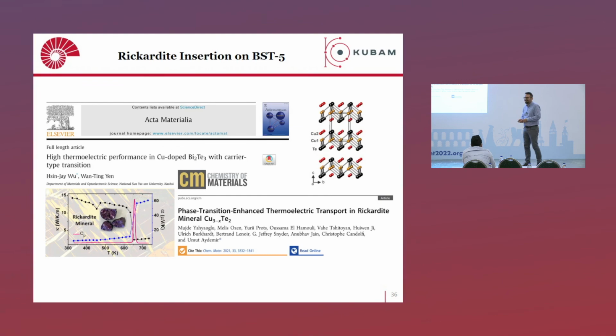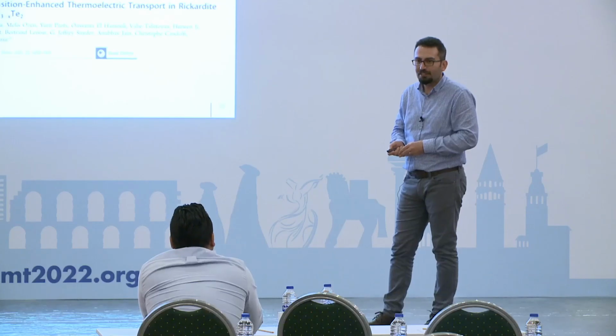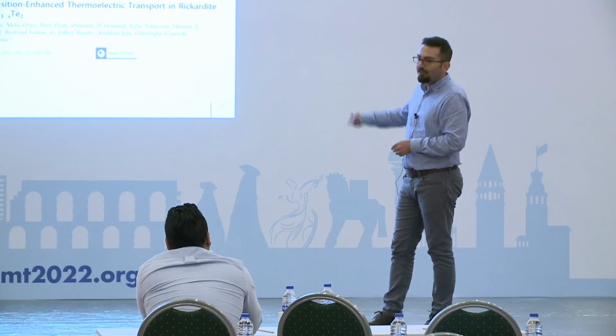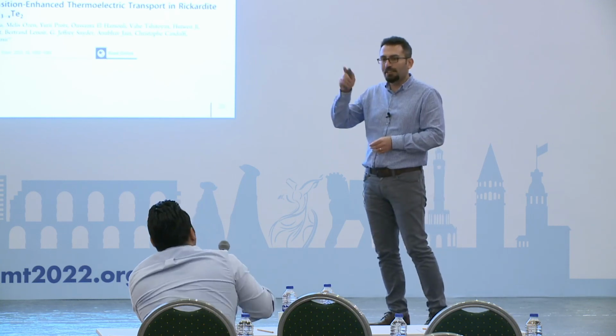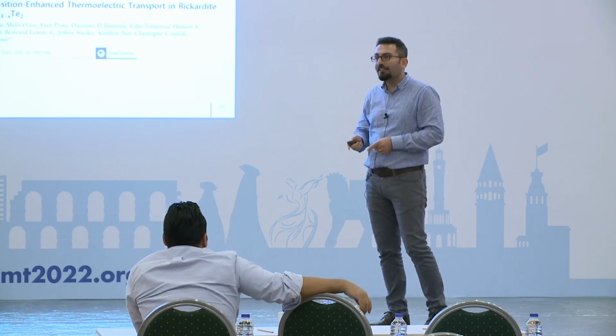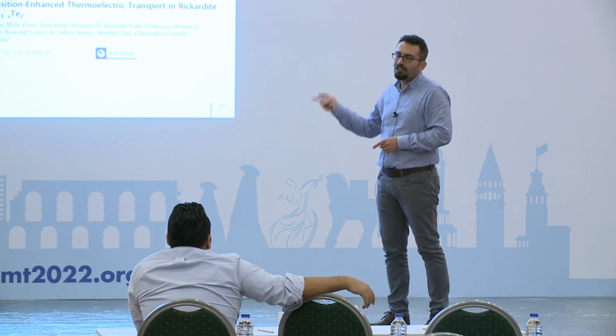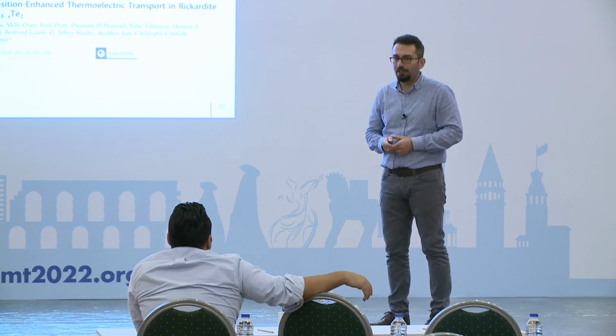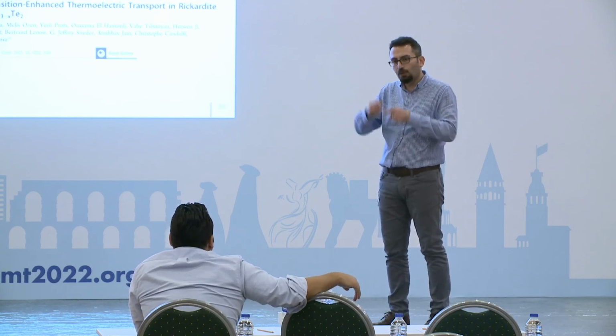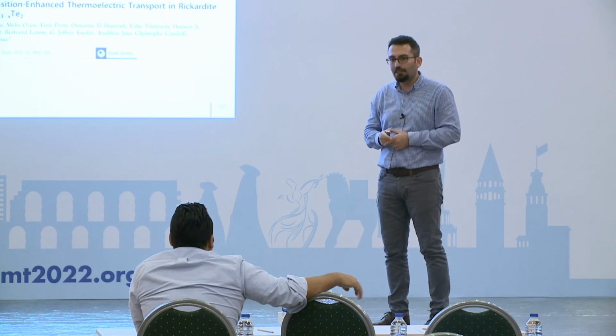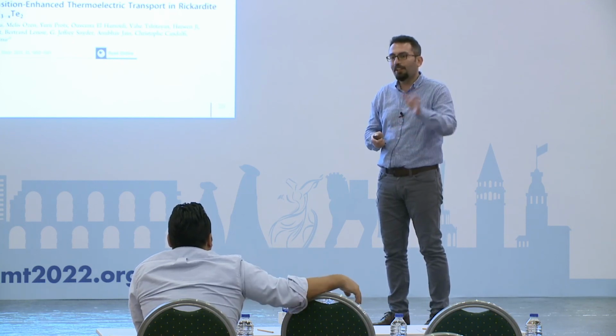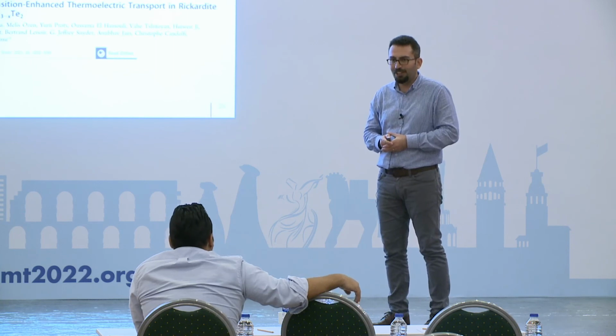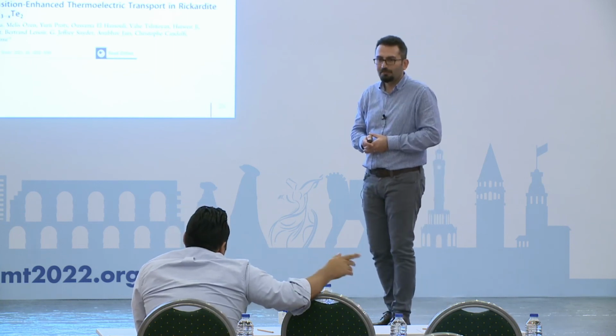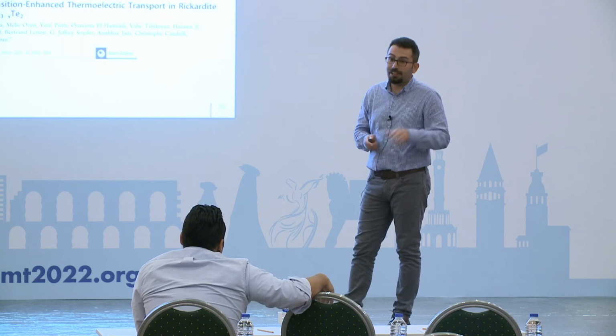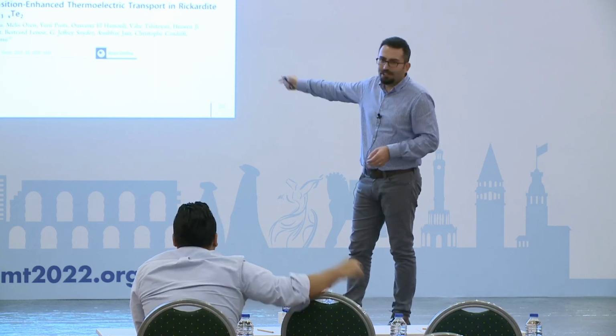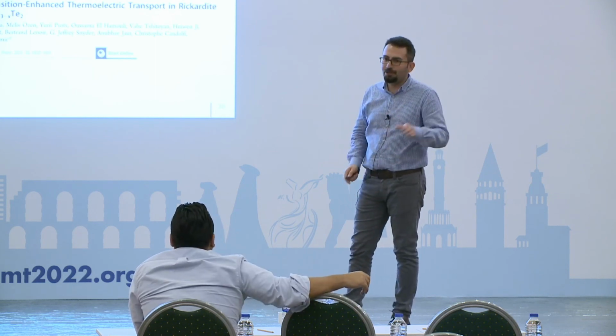Right. So about the N-type bismuth telluride, did you put some? Yeah, I didn't show it here. Yes, we tried some bismuth selenide telluride, and rather than copper telluride, we doped it with boron. Carbon-coated boron, and we could increase the ZT quite a bit. Around 20-30% increase, right? Because the biggest problem for bismuth antimony telluride is N-type. Exactly. Yeah, we did it as well. But here, I just showed these two results because this paper is also not written yet.